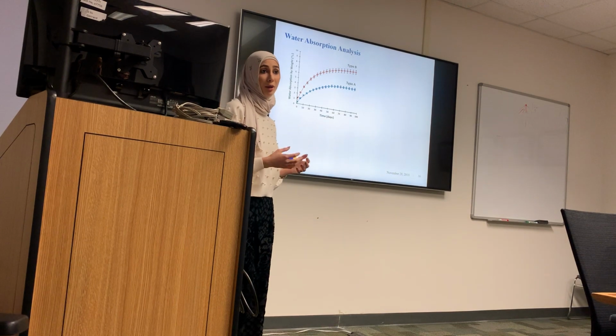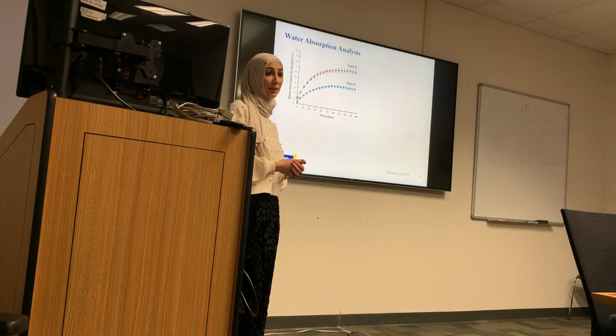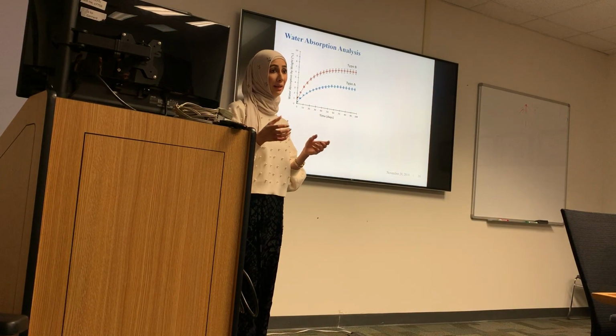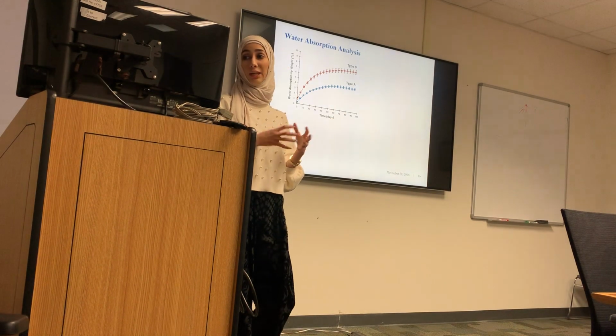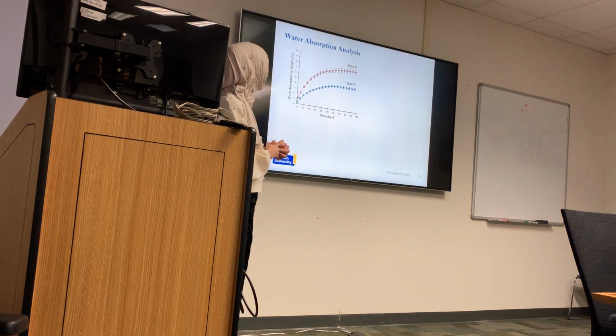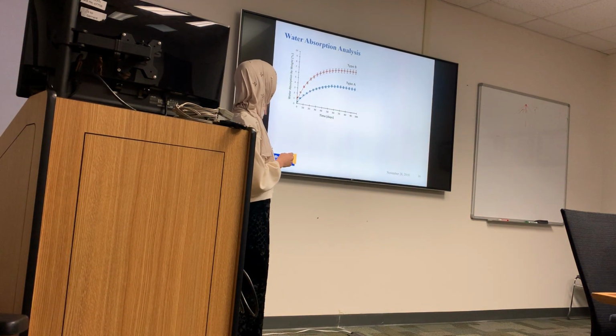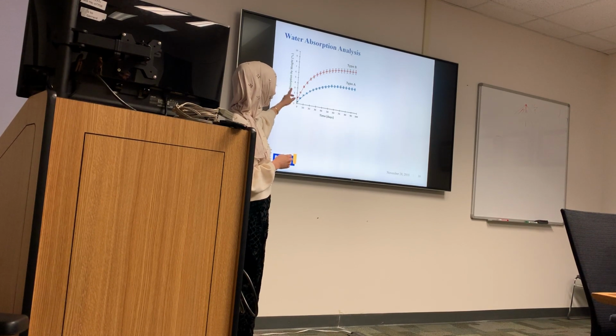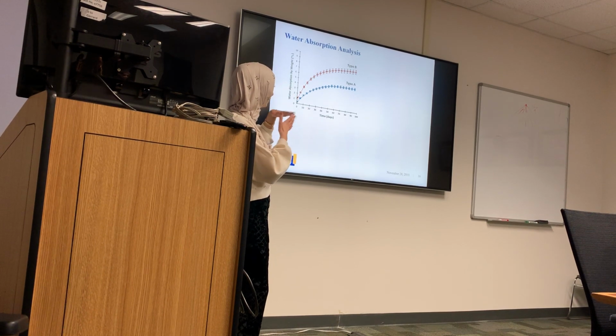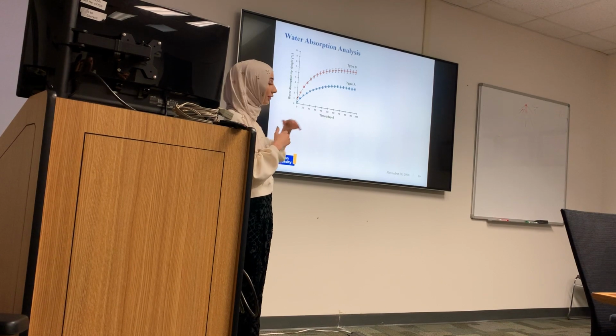I also carried out a water absorption test. What I did is I prepared specimens and immersed them in water for up to 90 days. We see here type A and type B show a rapid increase in water uptake for about 25 days, and then they saturated, so they level off.